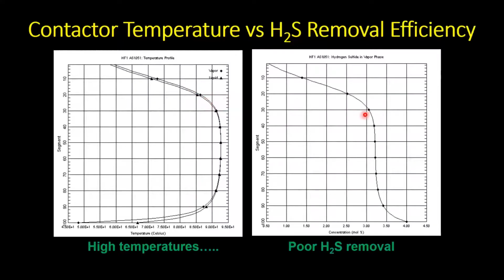And on the right, we're showing the H2S absorption profile. Typically, this goes from the inlet H2S, and then there's a relatively rapid decrease in H2S, and then this levels off and goes sort of straight up the y-axis here. But in this case, you can see we're picking up a little bit of H2S, and then there's no absorption of H2S inside 60% of that tower. And it isn't until the amine cools, again near the top, that we can actually get some absorption and removal of H2S.